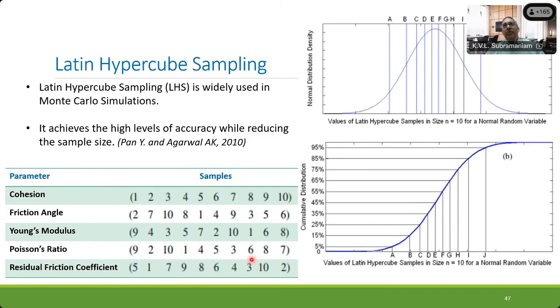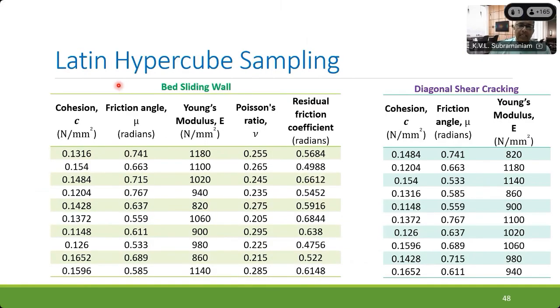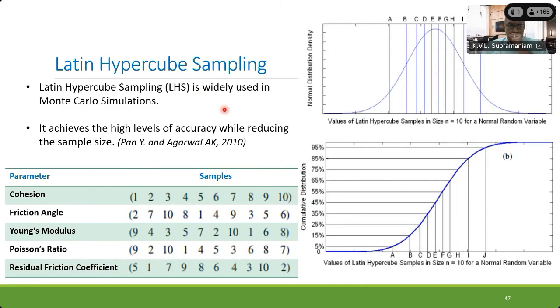Then the question is, how do I go about sampling these material properties? Because if I want to do something like a Monte Carlo simulation, there are way too many variables. I have ground motion variables, and then of course the material variables. There are 5 material parameters that we had: cohesion, friction angle, Young's modulus, Poisson's ratio, and residual friction. If I start varying them, I would run into millions of data sets. So we decided to use Latin hypercube sampling, which allows us to create random sets. Essentially, with the Latin hypercube, we are able to create a smaller data set, which, through this random sampling, allows us to capture a high level of accuracy while reducing the sample size.